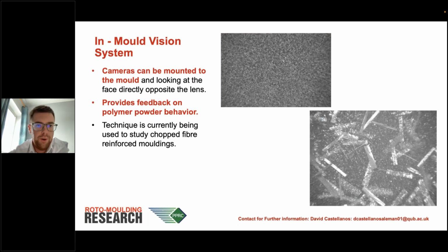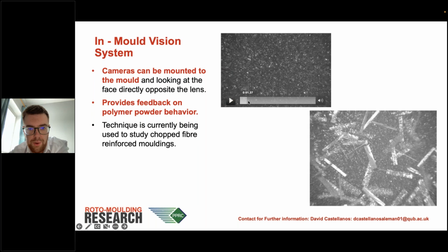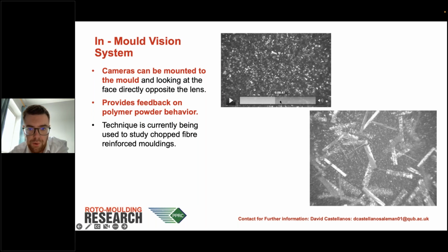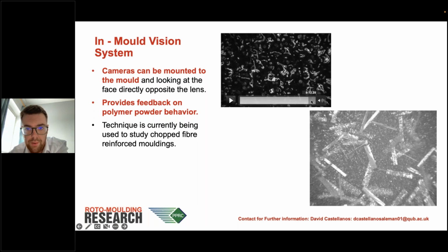So in the case of David's work, he's interested in trying to monitor the fibers within a molding. So he developed a camera system that is able to monitor the opposite wall from the camera. And this is what you see during that process. So this image is just a standard rotational molding cycle, and you can just about make out the bubbles on the surface of that molding. And then into the shrinkage and warpage phase, and you start to get a lot of reflection from the unevenness of the polymer melt as it starts to solidify.